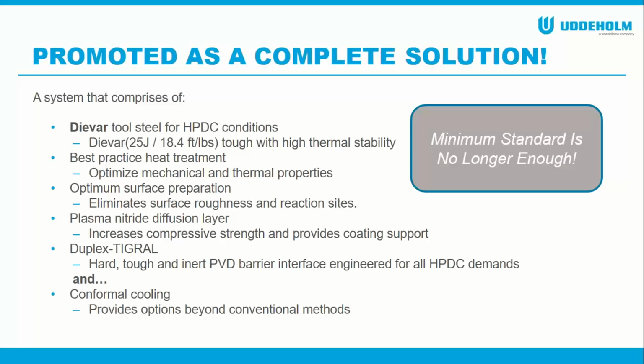So with this transition, now you have a substrate hardness of, let's say, 46, 48 Rockwell, followed by a nitride layer, which adds approximately 15 points to that. And let's say that is at 65 Rockwell, and then a PVD film, which is only microns thick, 2/10 for those of you that are imperial. That would add even more hardness to that. It's beyond the Rockwell scale, but you're looking at 3,500 Vickers. So you could see the perfect transition in hardness. Last but not least, again, conformal cooling, which will provide options beyond conventional methods. So it's a nice complement to the system.